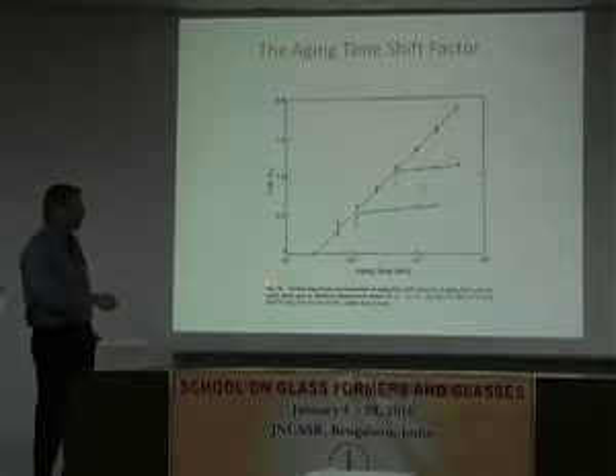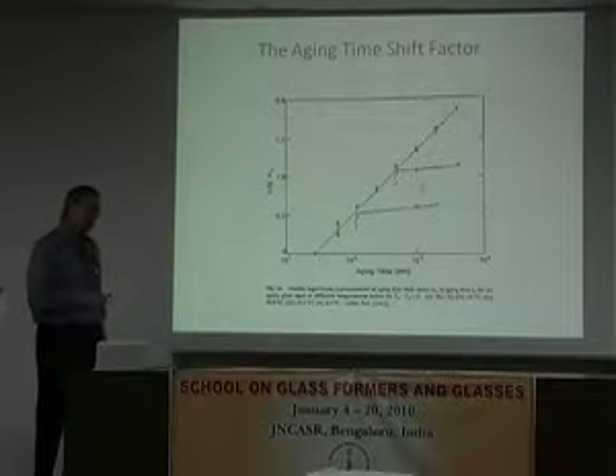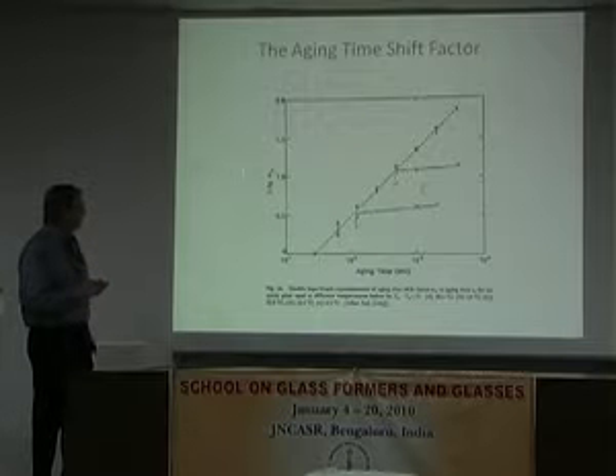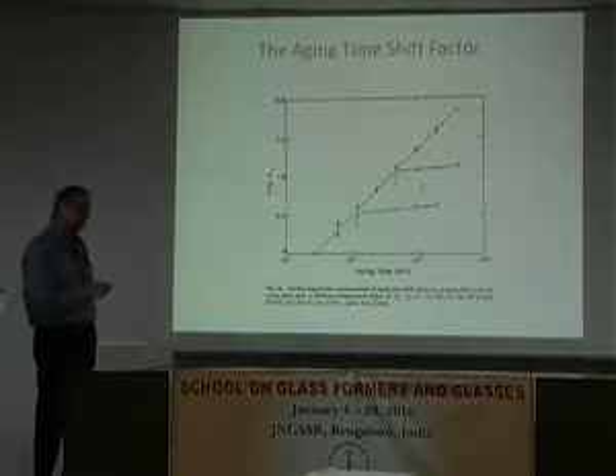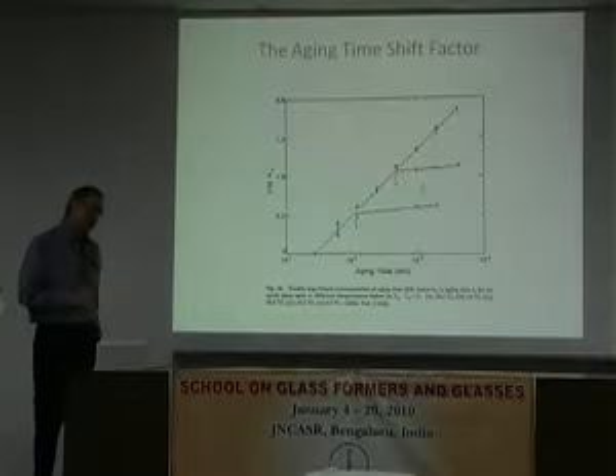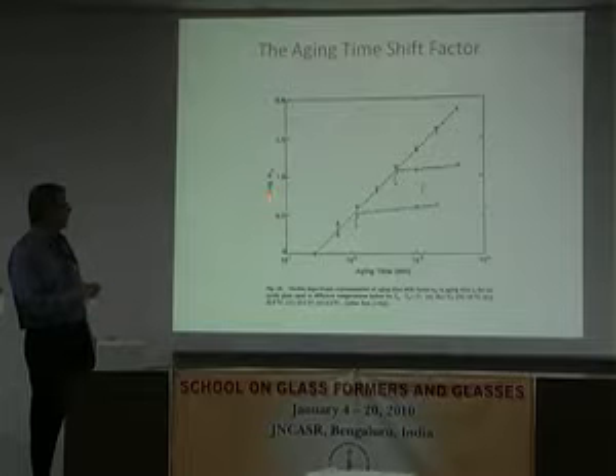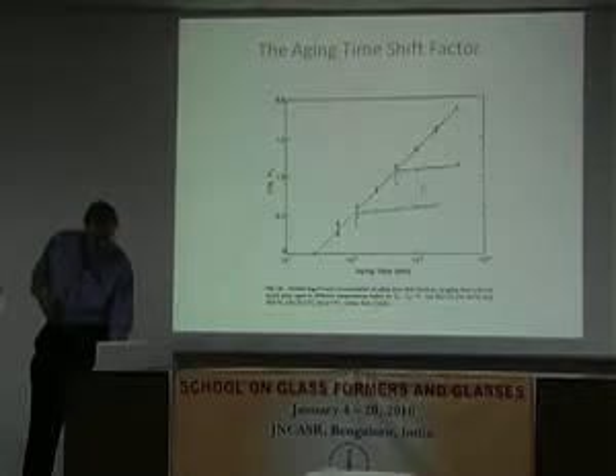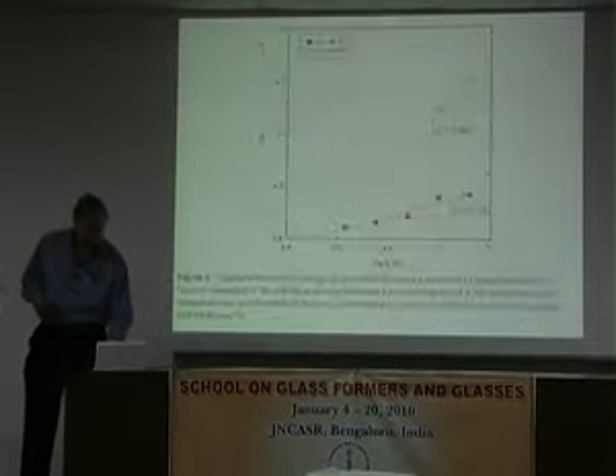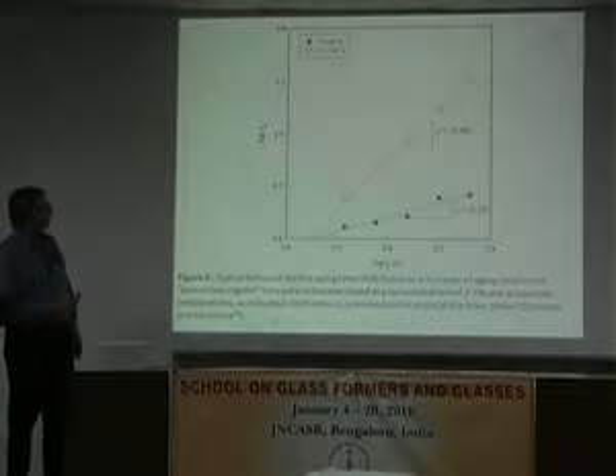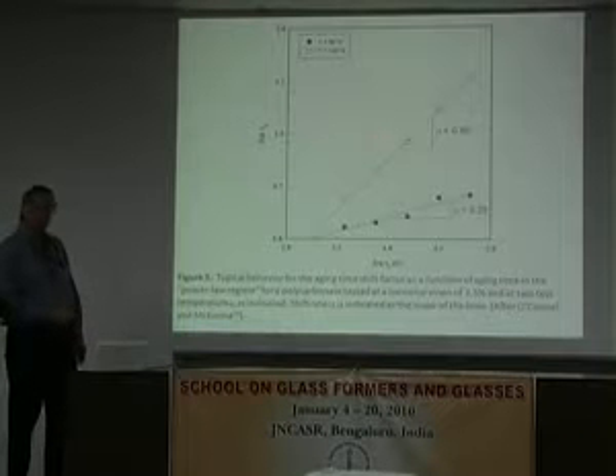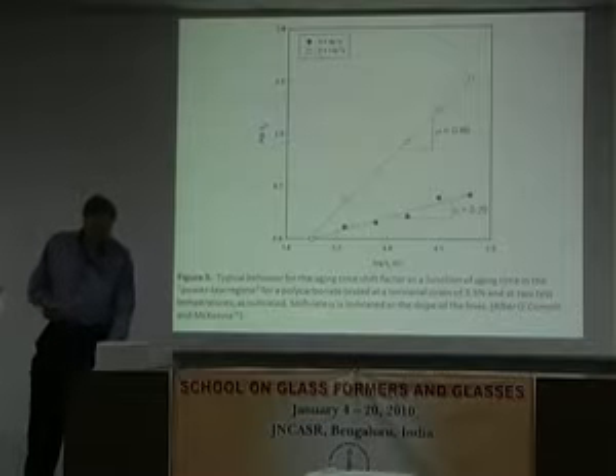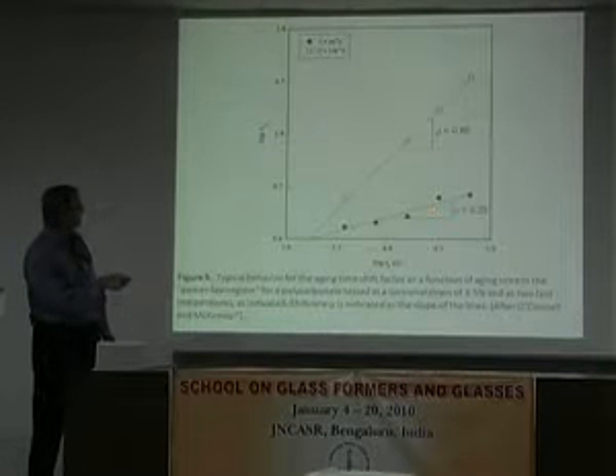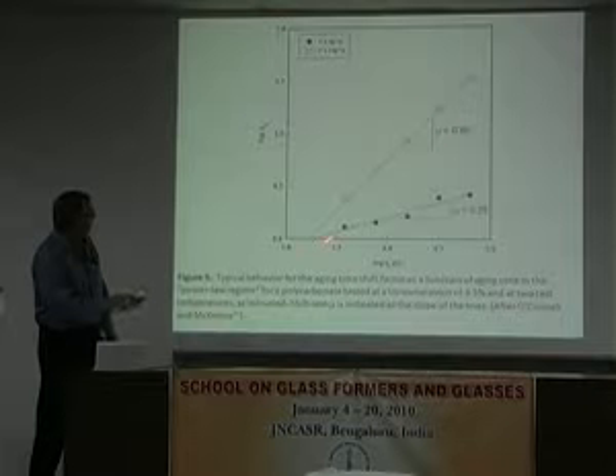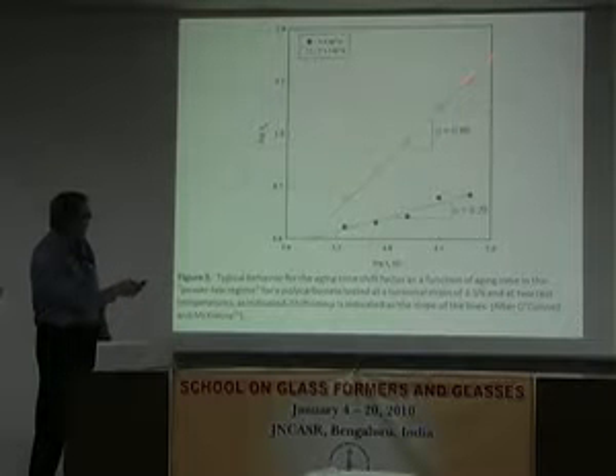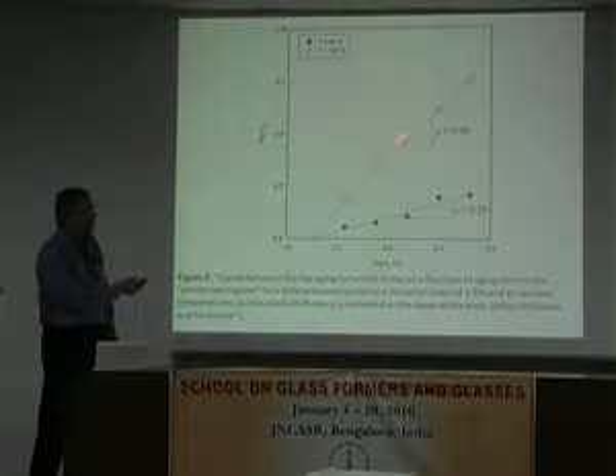This is the shift factor. This is the aging time. The shift factor is really the relaxation time normalized to a reference relaxation time. Okay, so if you like, it's a scaled relaxation time. And this is polycarbonate. It just shows that depending on the temperature, my shift factor can depend quite a bit on temperature. This is way below Tg, and this is actually in the region where it goes through a maximum. It's almost 1.